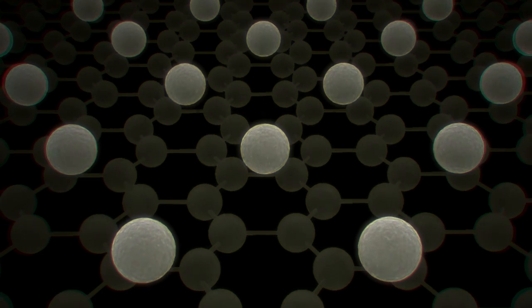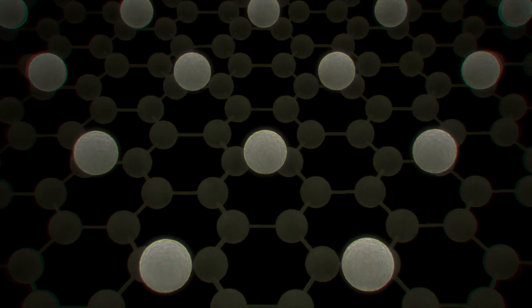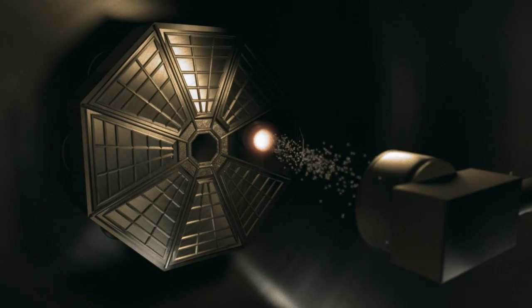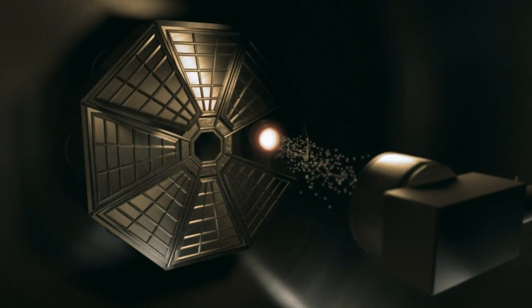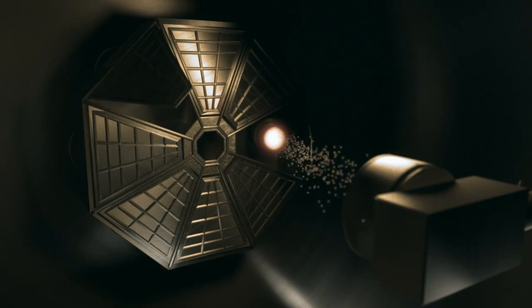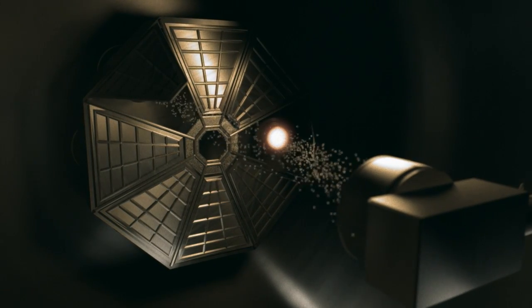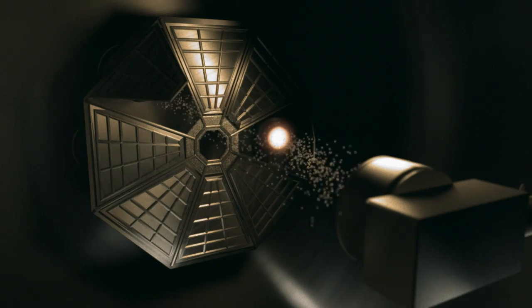At the bottom of the gallium droplet, next to the graphene surface, the gallium atoms try to match the carbon hexagons by arranging themselves into a very unique hexagonal pattern. At this time, we now also open the flange to the arsenic source, so that both gallium and arsenic atoms are directed simultaneously towards the graphene surface.